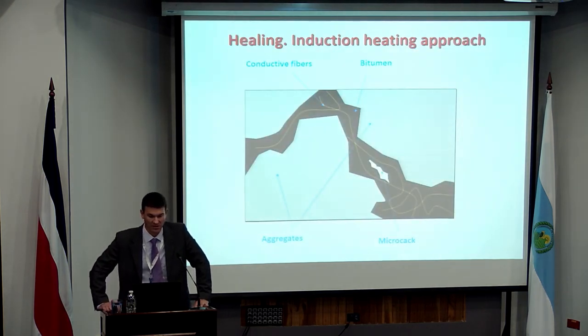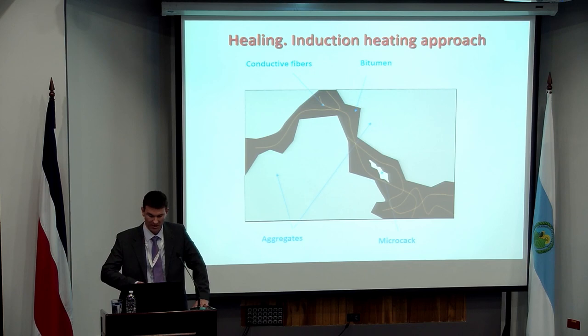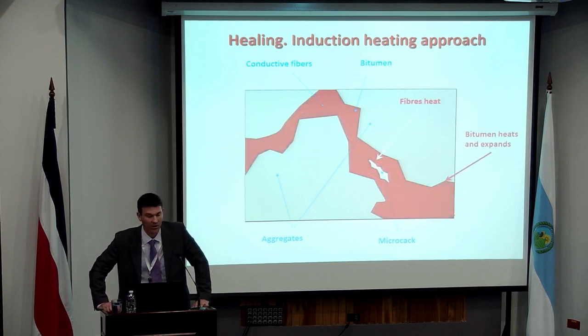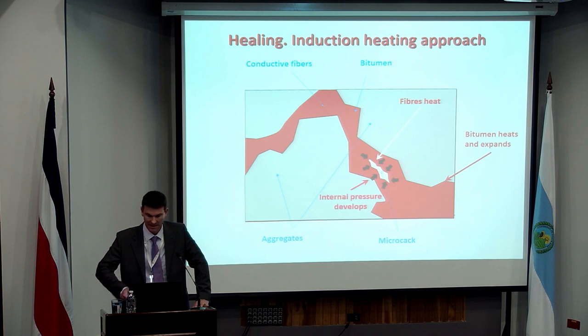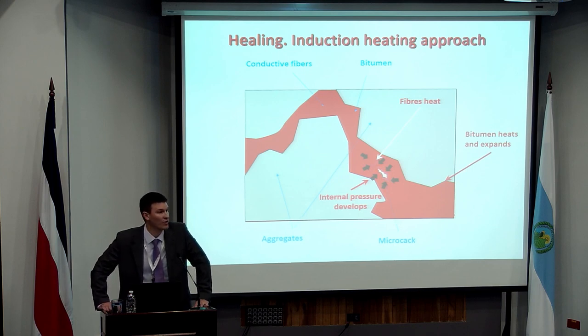And then you're going through a process. And the process is very simple to illustrate through these next few slides. You've got your steel fibers, you apply your induction heating, it locally heats up your bitumen or your mastic, it expands, and it very quickly closes up that particular crack and either reduces it completely or reduces it to a degree where effectively you can retain some of your initial strength or your initial stiffness.